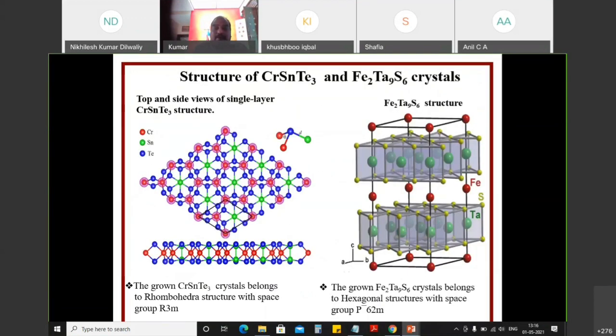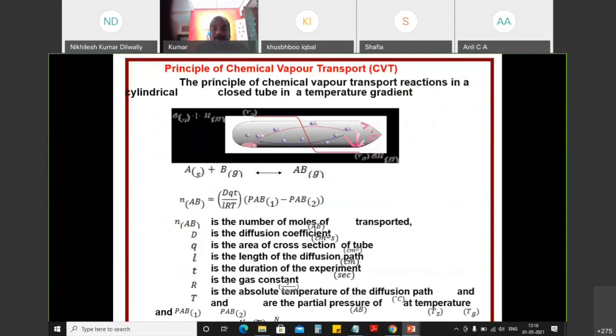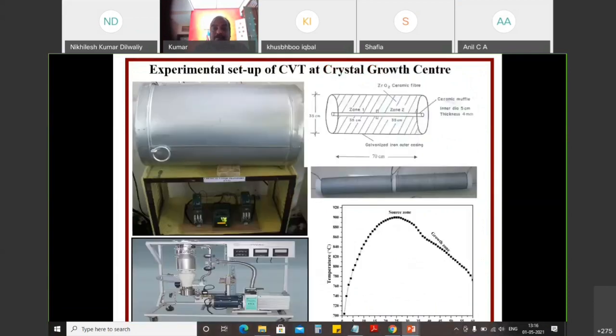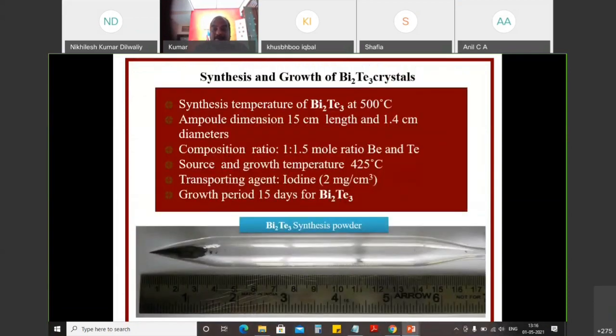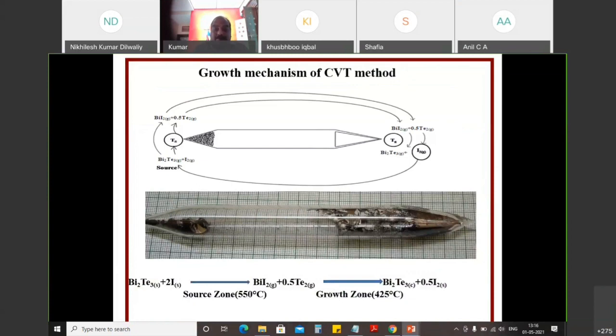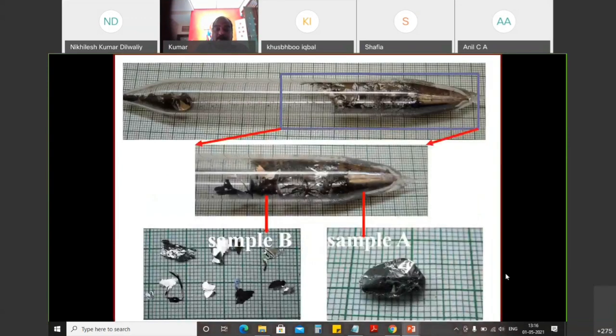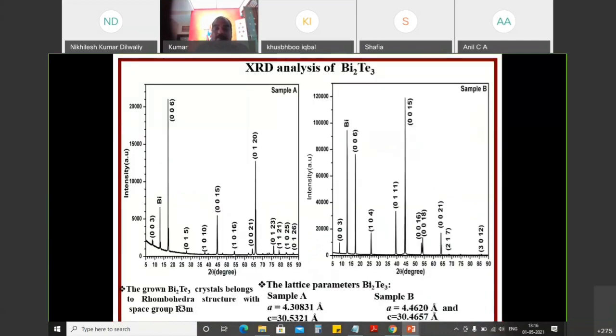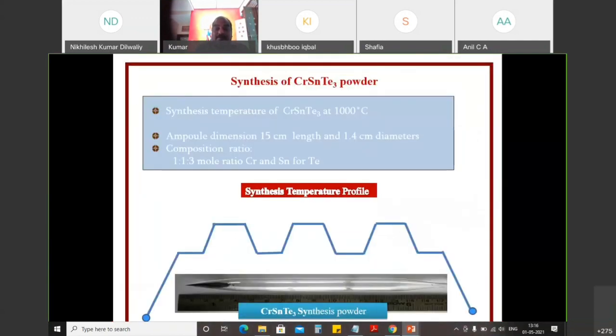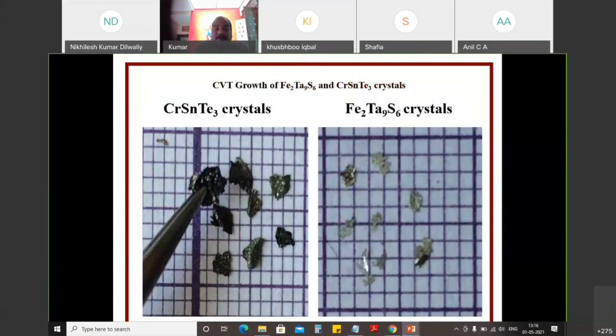So we have tried to grow these materials which are of interest for topological applications. We have grown bismuth telluride, then chromium tin telluride, iron tantalum sulfide. I'm currently trying to grow zirconium telluride. This is grown by what is known as chemical vapor transport, in which bismuth and tellurium are mixed, and there is also a transporting agent, which is excess tellurium. So this grows as bulk crystals, which can be cut as flakes and then used for specific device applications or for fundamental investigations.